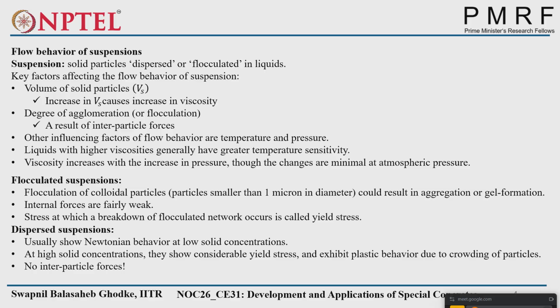You can read much detail about which one? Hydrogen bond. Yeah, but a hydrogen bond will not be possible in this case. Most cementitious particles will be held either by van der Waals force or, due to hydration, by CSH bonds that will form. Yeah, that is a chemical bond. Another important sentence is that the stress at which the flocculated network breaks down is called yield stress. Whatever we measure from the rheometer, that yield stress is basically the breakdown of flocculated networks, right?